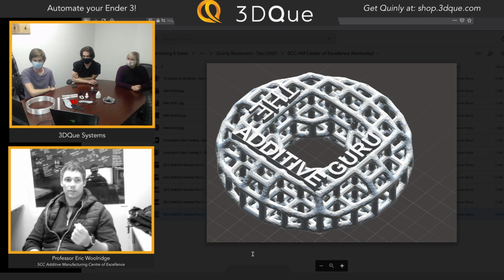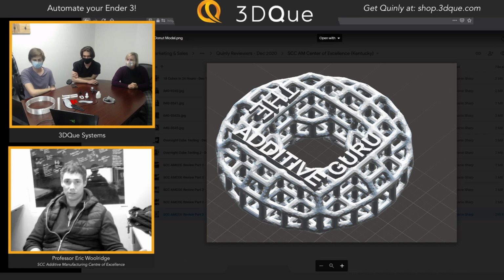That's the power here. And what we've also noticed is that in the more exotic designs, lattice structures and also using generative design, like with Fusion 360, we are able to address the Z-axis weakness through shape change. And we can take a PLA part. Yeah, it may not do that great in heat, but I can make the part still super strong to the forces that you plan on applying to it. So that is probably the biggest part of the story in all of this.